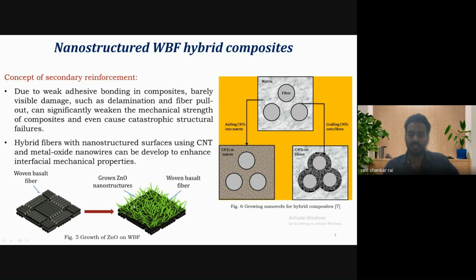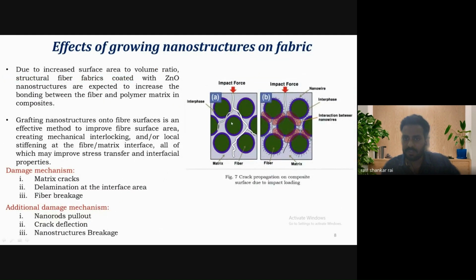This is a plain BFRP composite, and this one is a ZnO nanostructure reinforced polymer composite. Here you can see there is an interfacial interaction between the nanowires and the polymer, and the basalt fibers also. So overall, you can see an enhancement of the interfacial characteristics. Due to the increased surface area to volume ratio, fiber coated with the ZnO nanostructure is expected to increase the bonding between the fiber and polymer matrix. Grafting nanostructure directly onto the fiber is an effective method to improve fiber surface area, mechanical interlocking, and local stiffening also. Along with that, there is less chance of agglomeration, and the porosity is also minimized.